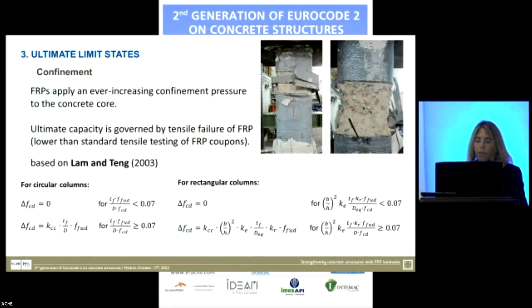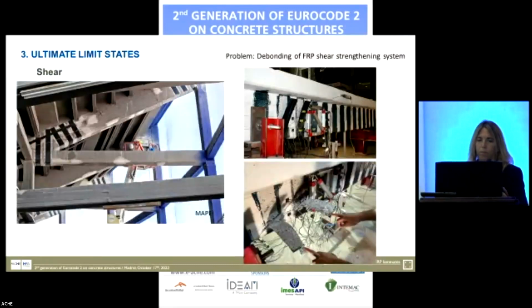And here we have a formulation included in Annex J in order to obtain this increment that we can have in the concrete strength, considering different configurations, circular or rectangular columns, because the confinement is more efficient in circular columns than in rectangular ones. And this formulation is based on Lam and Teng, 2003. We can also strengthen in shear with different configurations that I will show you in the next slide.